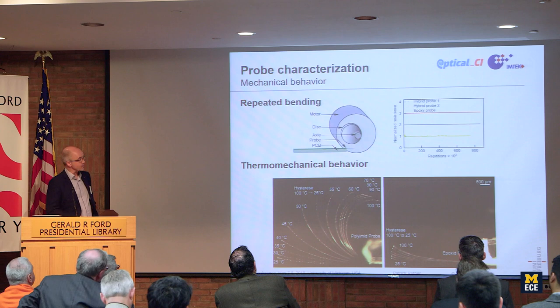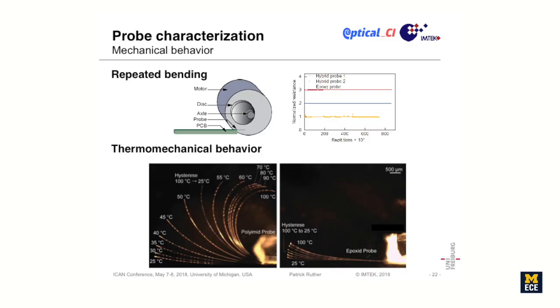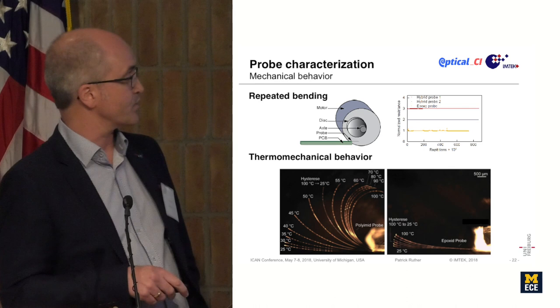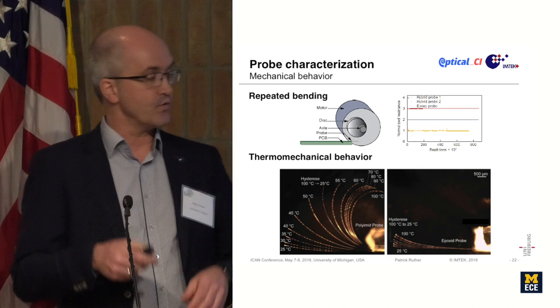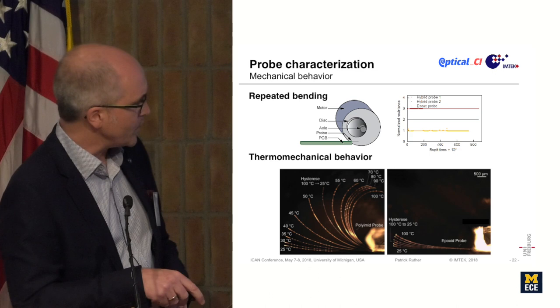So what we did here is we did a bending test of roughly 1 million bending cycles, and the probe by itself didn't fail. More important for us is the thermomechanical behavior, because during the encapsulation, we have to expose the probe to temperatures around 100 degrees. And what you see here is the polyimide probe bends as you increase the temperature. So it bends up, and when we cool down, it relaxes, but we obtain a hysteresis here, and that's, let's say, a bend by roughly 90 degrees.